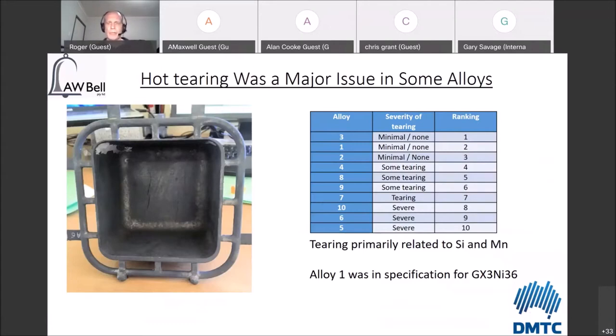But what was really nice was that alloys 1, 2, and 3 showed little to no hot tearing at all. And of course, the big positive out of that was that alloy 1 was actually in specification for the ISO alloy and also showed no hot tearing. So that was a really, really nice result to be able to achieve.